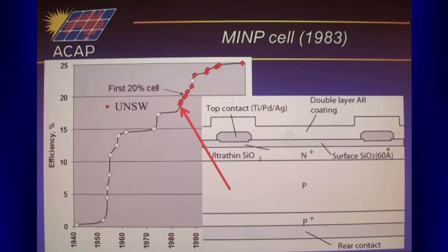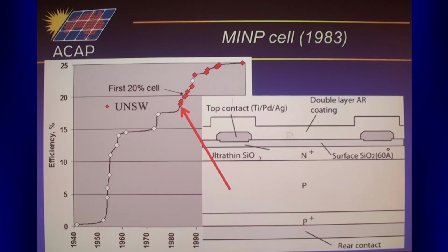So that structure, and you'll notice we have no texturing, it's just a planar device structure, but we're still able to beat the black cell efficiency record. So essentially what we're doing by this approach is we're just reducing the flows of carriers both in this region here across to the contacts, across to the surface. So you can regard this as a lot of one-dimensional things all together in parallel, but there's a flow of holes to the surface here. That's going to be reduced if you have a good interface here. And then the flow to the contact is reduced by having this oxide layer here. So you get improvement both in contacted areas and non-contacted areas with this approach.